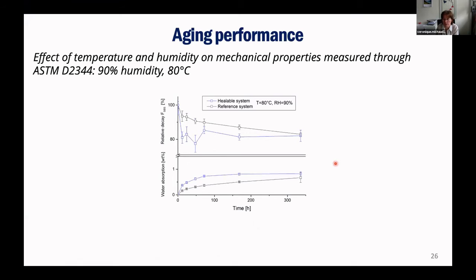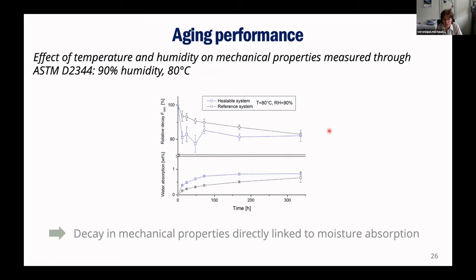And then we also did a bit of aging performance. So we looked at what happens if you put this stuff in humidity at 80 degrees for some days. And then we saw that compared to the reference system, indeed, we absorb a tiny bit more water, but it's still manageable. We have a little bit of decay after SBS, so the toughness of the material after this aging, but not that so much worse than epoxy.